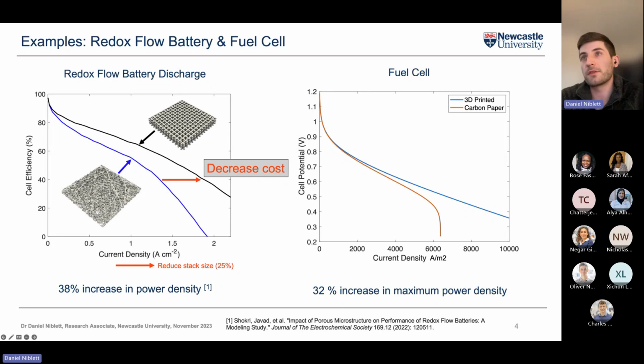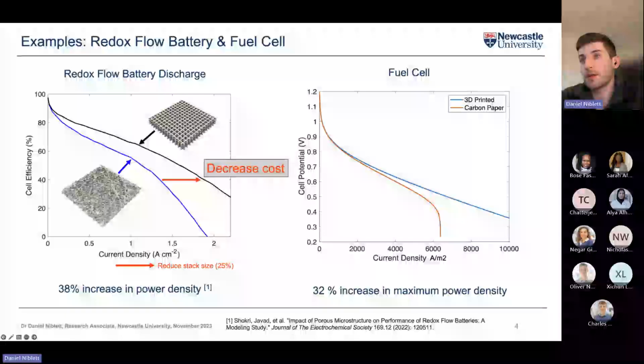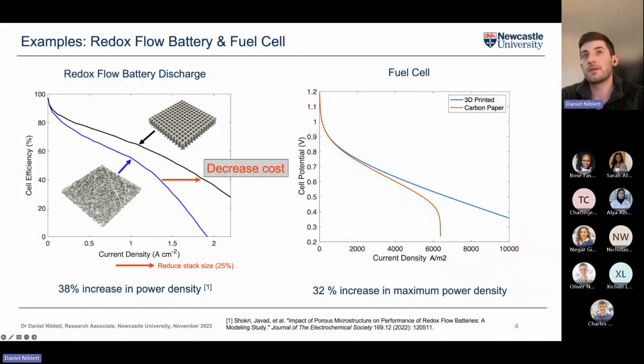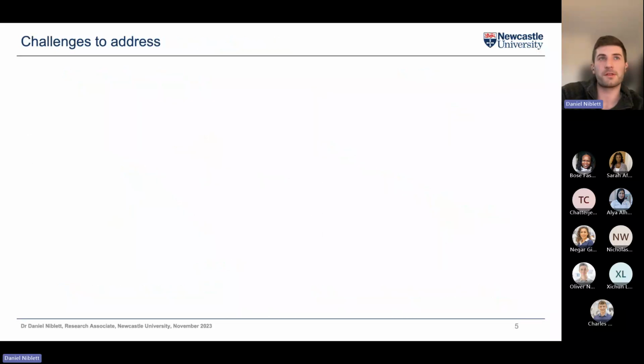And again, the same for a fuel cell. The 3D printed is the line above the orange line. And what that essentially means is you're getting more energy as you put more throughput through the device compared to if you're using the traditional carbon paper type material, which is something like you're seeing on the left here by this reconstruction of the carbon paper. And so there's some motivation there to say that potentially if you could design and manufacture a new type of microstructure, then you might be able to improve the performance of different electrochemical devices.